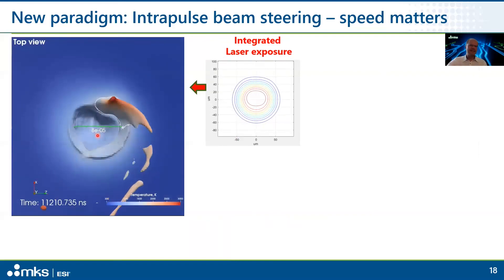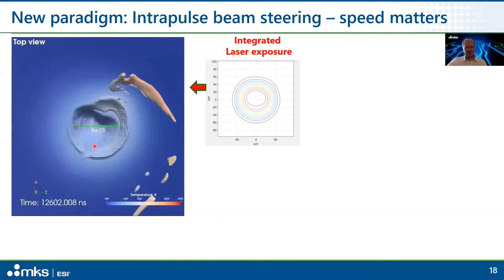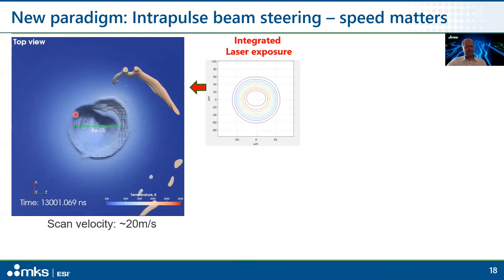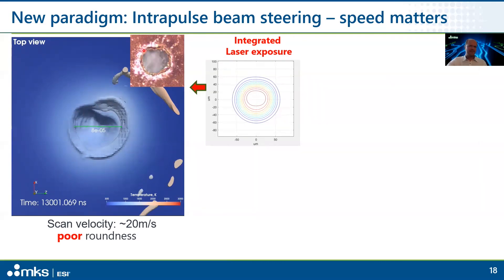This is impossible to do with the galvo because the galvo is far too slow. But doing this with our first model, you can see that we're actually not getting a round via — we have this cardioid shape — and the first via drilled actually bore that out, showing this little kink. This kink is actually important: PCB houses have a great desire for pristine round vias for proper yield of the plating process, so this result is unacceptable.